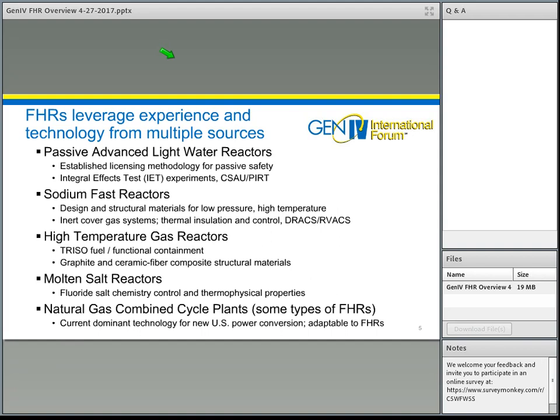And it's one of the interesting things about FHRs, because they can use these ceramic structural materials in the reactor core, and because the coolant provides a very effective heat removal, particularly by natural convection, what we find is that in transients and accidents, there's very large thermal margins to fuel damage, typically hundreds of degrees centigrade. And so the design of the reactors really focuses on keeping structures that are outside of the core on the coolant boundary within the acceptable temperature ranges.